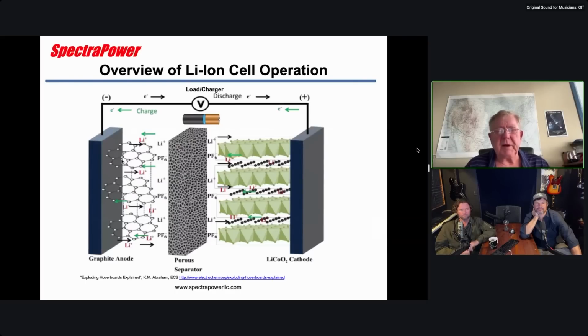So if you have big particles, which might give you higher energy density, well, it takes longer for the lithium to intercalate into the particles because it's actually moving into these planes physically. And so the bigger the particle, the further it has to go to get into the plane of the graphite. So if you try to move it too quick, then what will happen is what we call polarization. And when you think about it, these lithium ions, when they come up to the graphite particles, they don't just sort of hop into it. There's actually a pretty complex